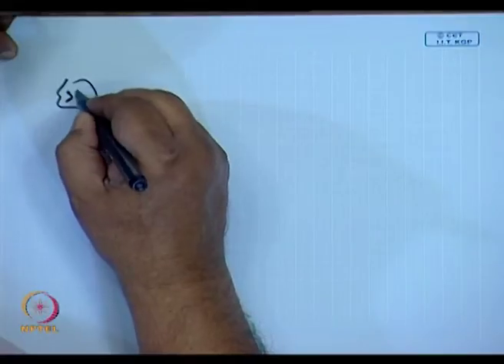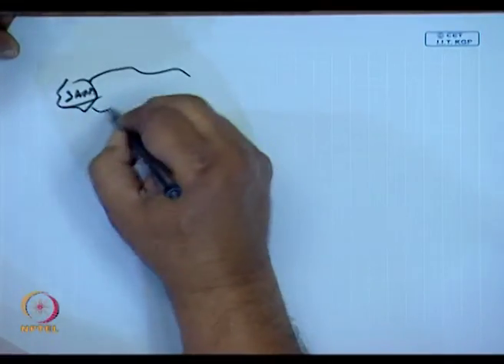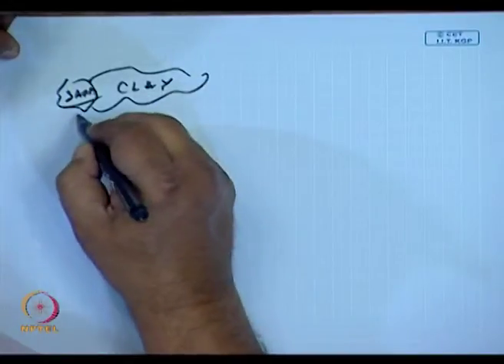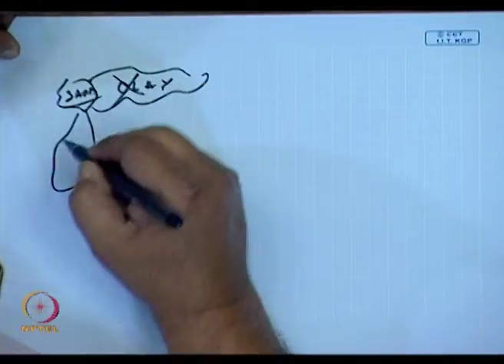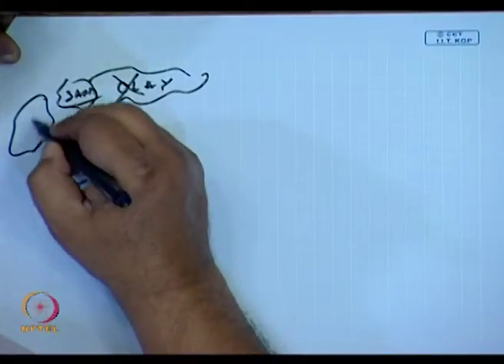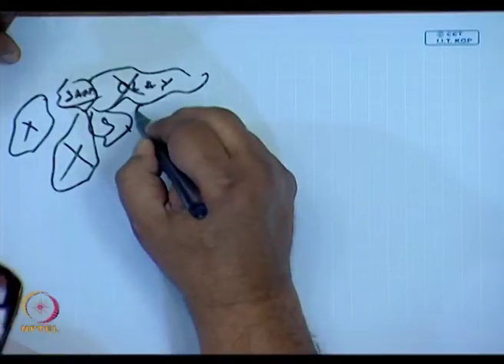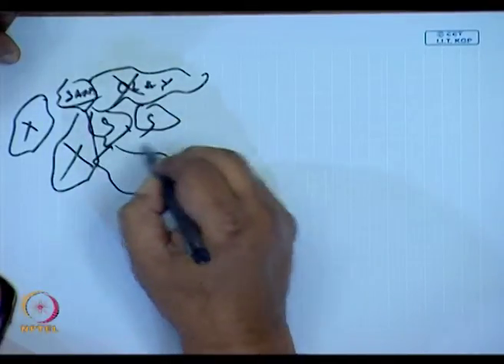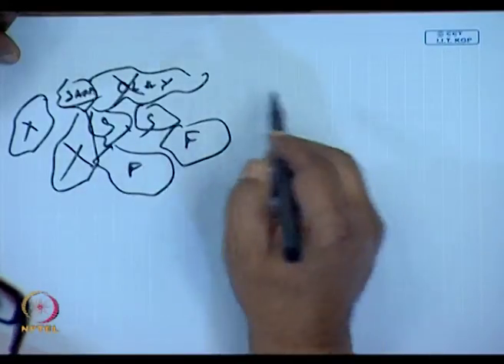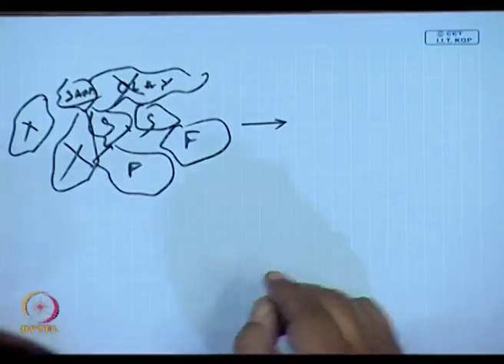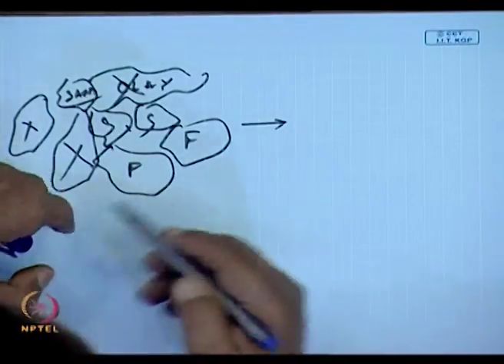Now if I take the material and look at it under a microscope, what will I see first? What I shall see is there will be sand grains, there will be clay particles, a lot of clay particles. Let me mark the clay by X. There will be a lot of sand grains, let me mark it by S. There will be some feldspar also. This is how the thing would look under a microscope. When it is heated to 800 degrees centigrade, what happens is that feldspar melts.